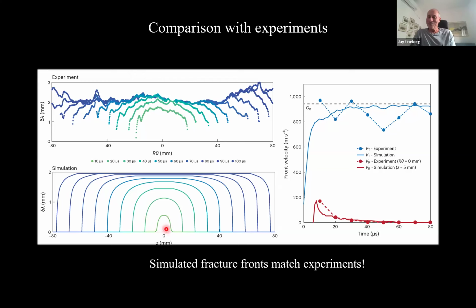But okay. At the beginning, Gabriele did exactly that. He induced a patch. How large should the patch be? By trial and error, he took the smallest patch that you need to induce for self-sustained propagation. The patch is localized, sub-millimeter to a couple of millimeters, but once you go out of the patch, at the third time step, the crack in all dimensions is already much, much larger.